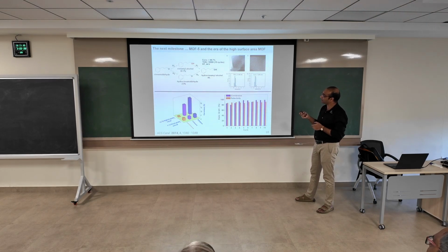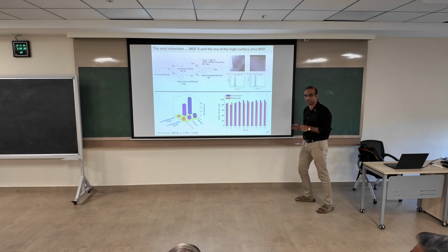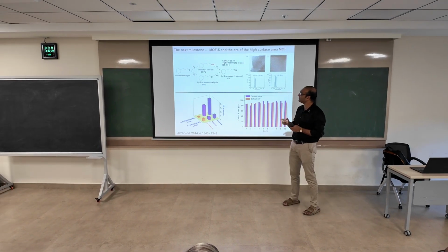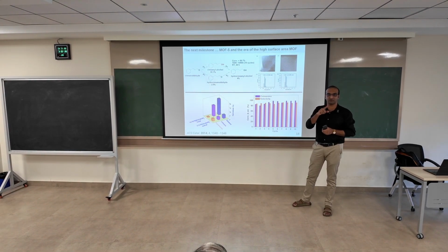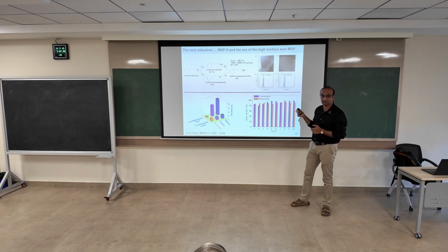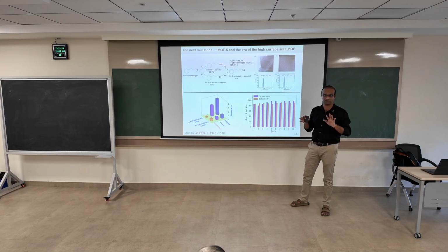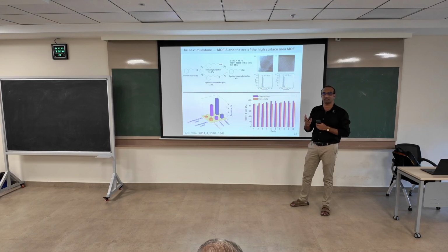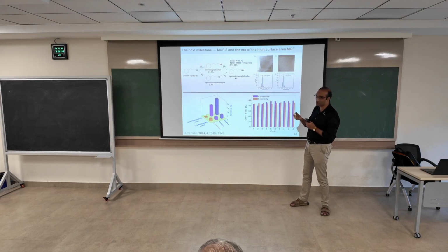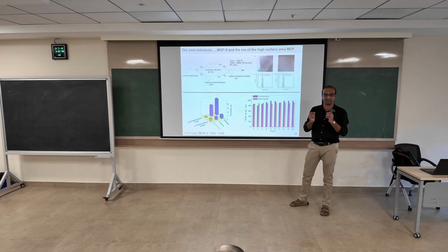And one more advantage of these MOFs, especially UiO66NH2, is that you could go from a loading of 1% to 10%, and we even tried 40%. It's still 1 nanometer, okay? Because there's that much space inside the MOF to contain these platinum ions, and when you reduce them, you'll get the particular size, okay?